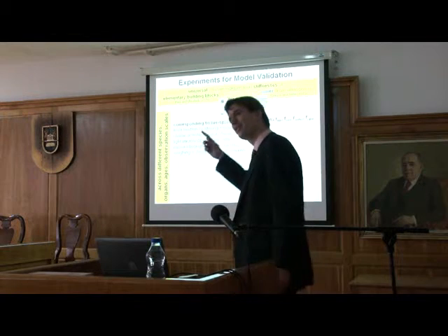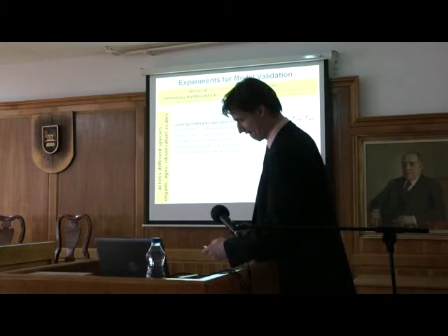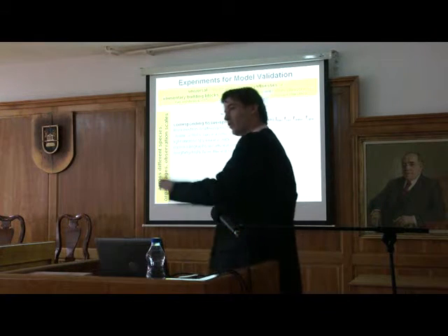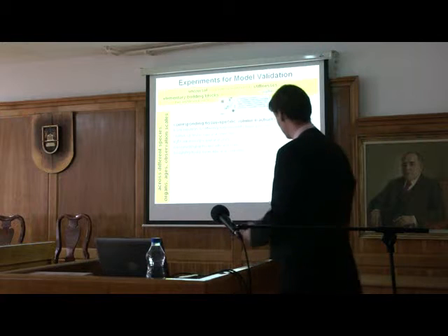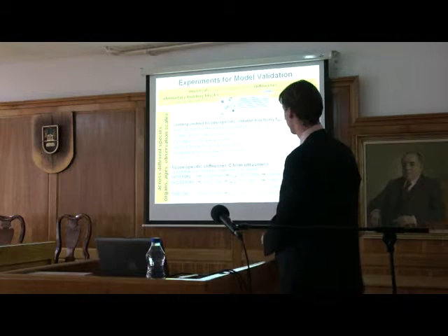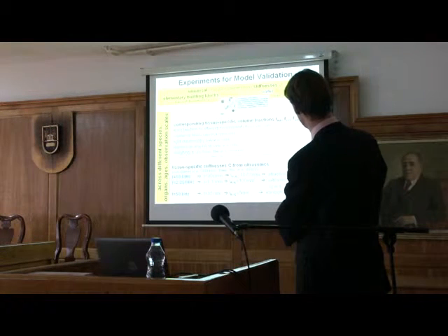Or we take it directly from experiments, a little bit historically, because this model was older, so we did it first directly. And now with the rules it's even simpler. So we put a lot of different volume fractions into one and the same model. The model gives us a lot of different elasticities. And then all these different elasticities have to be tested by a lot of different tests at different frequencies, delivering us the stiffness of this material, small, larger, larger.